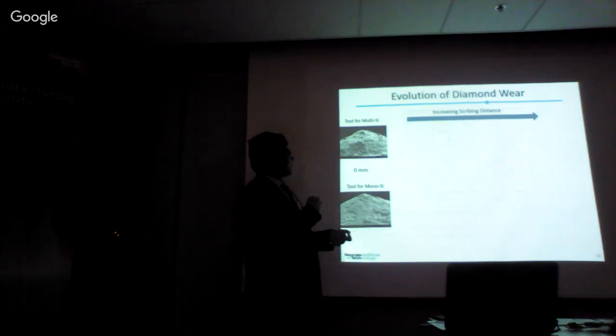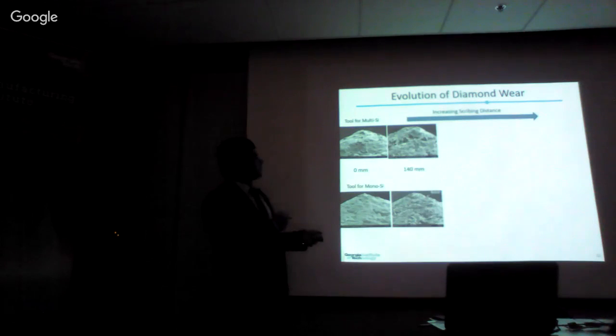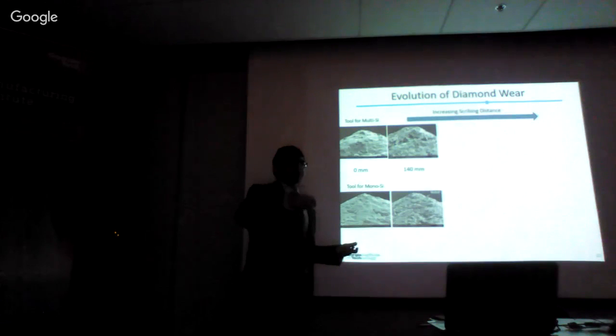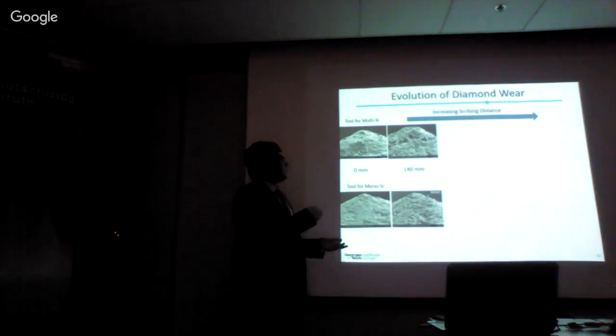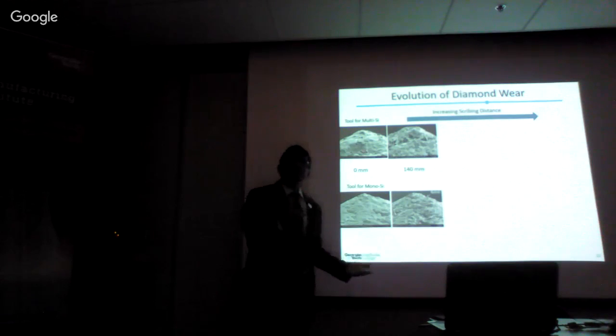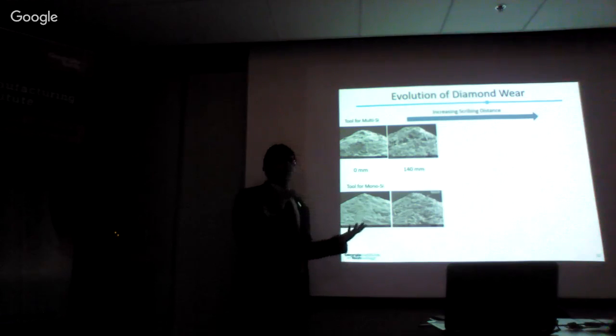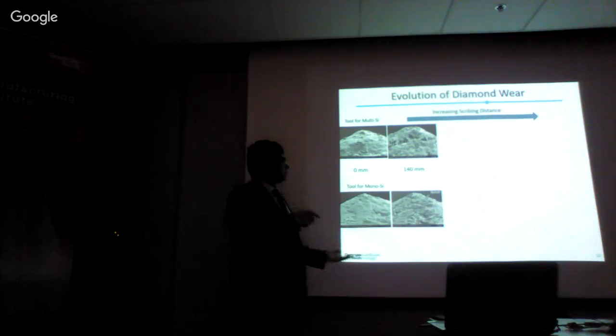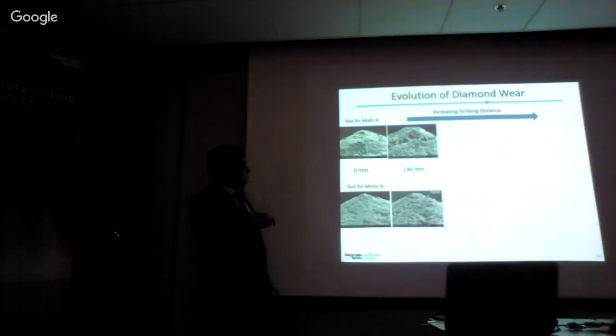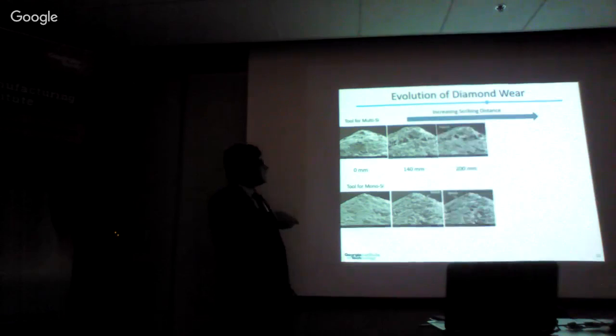Moving on to the evolution of the diamond wear, this is the condition of the abrasive at 0 millimeter, which is before scribing. As soon as we scribe for a distance of about 140 millimeter, we find the top of the diamond for the tool cutting multi-crystalline silicon has been blunted off. And this is similar to what we see in our actual wire sawing process, where we saw the diamond had blunted. The tool for monocrystalline silicon develops some notches on this side.